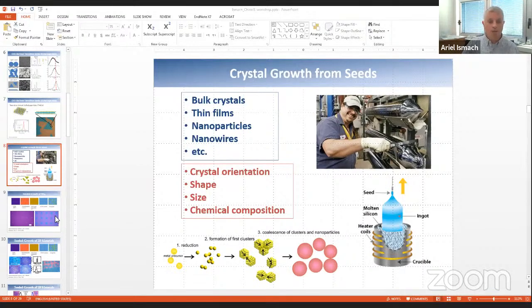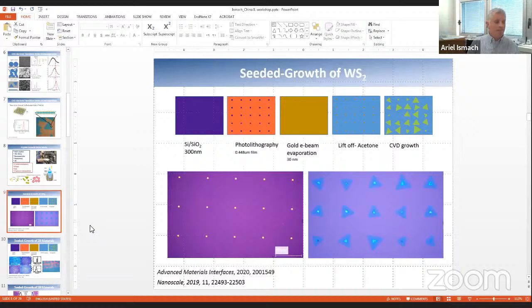So we implemented this seeded growth approach using a very simple photolithographic methodology in which we pattern islands of different metals. Here you can see islands of gold. And then we do the chemical vapor deposition. And you can see very nicely that as long as the surface diffusion of the different precursors is larger than the seed distance, the seed pitch, you have preferential nucleation at the seed location, and therefore you can continue the growth from this seed. And this is the main idea.